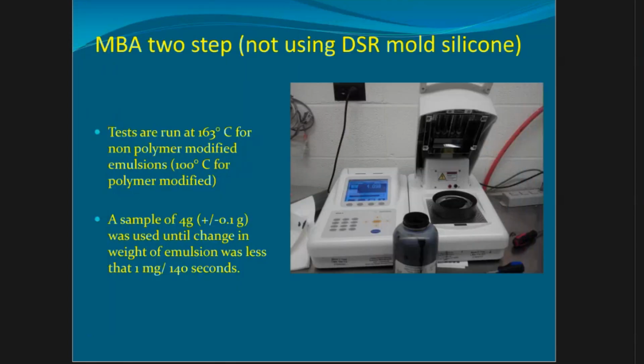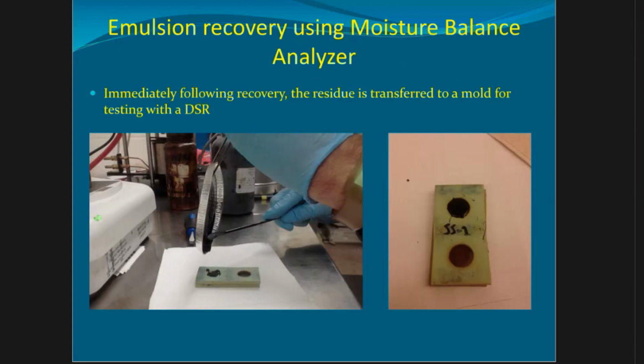So this is what the University of Texas did. The way they did it, they first recovered in this, so it's what I call a two-step process, and then put it in the DSR mold. And everything is fine. I contacted the plant to get the emulsion, but I said, before you send us an emulsion, send us the asphalt that will be emulsified. In the paper, they show results for the original asphalt and then the asphalt that was emulsified, and those numbers are within, I don't know, 5% of each other.